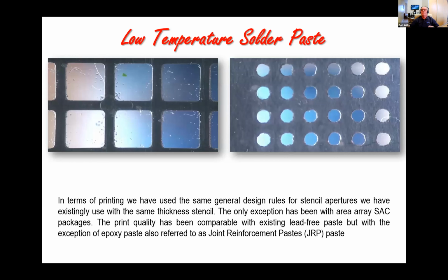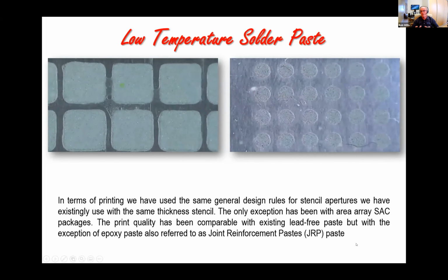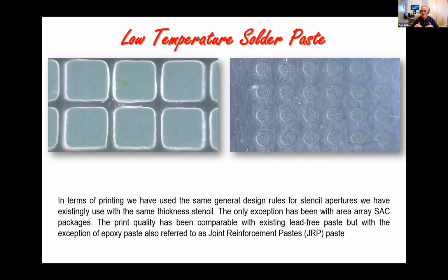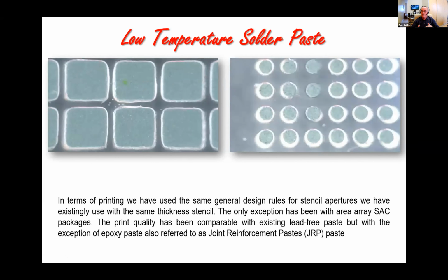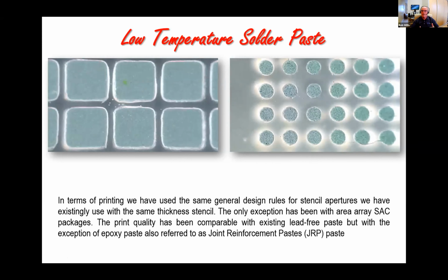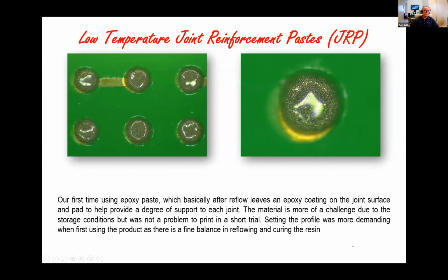The only issue that I found is some of these joint reinforcement pastes, which I'll explain in a moment, weren't quite as easy to print as traditional pastes. And these are just two examples of trials that I was doing. Here we're printing onto a glass substrate and then measuring and looking at the variability of the amount of paste that's actually applied during the printing process and some of the other characteristics of the material. But it's a good way of understanding what's actually going on in a process, and something that is useful also during paste evaluations. This is just a close-up of these materials.